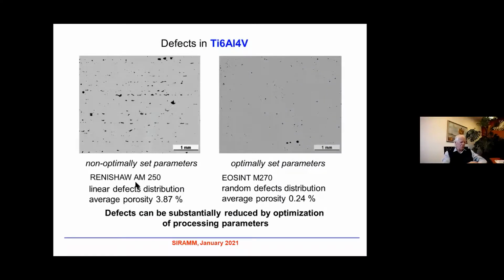Let me show some examples of microstructure of titanium alloy. On the left-hand side here, you can see the microstructure of non-optimal material, which was produced on a Renishaw AM250 machine with not optimally set parameters. You can see that the material has many defects and the average porosity is nearly 4%. Such material is naturally not very good from the point of view of fatigue behavior.